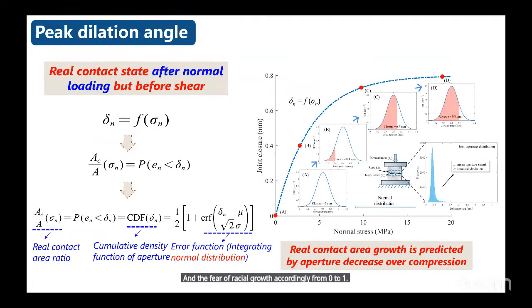Thus, the key to predict the peak dilation angle is to quantify the contact states after normal loading but before shear, since when we are doing a direct shear test or considering the rock joint in the field, they are confined by normal stress. Since the contact states of the rock joints change over the normal loading, we treat the real contact area growth process as a consequence of the joint aperture reduction from zero normal stress to the prescribed value, and we assume that the joint aperture follows the classic normal distribution.